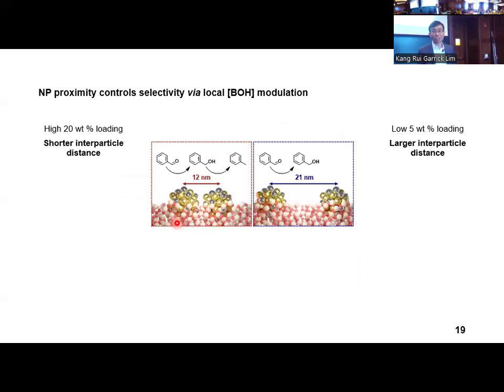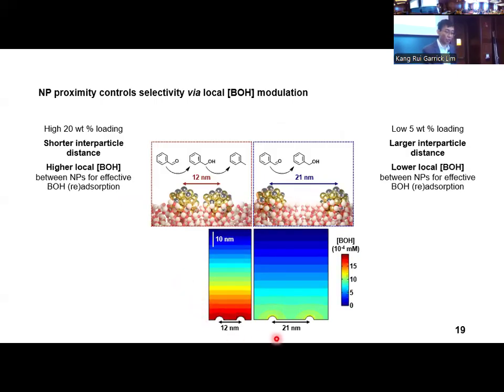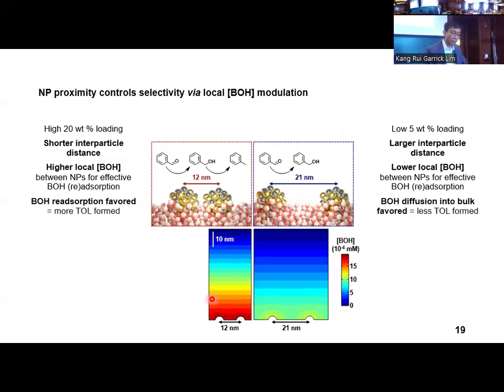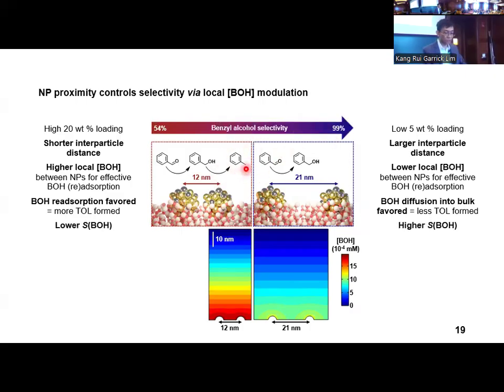Now we can combine our findings all together. Catalysts with a shorter interparticle distance exhibit an enhanced local benzyl alcohol concentration profile between the nanoparticles. Thus, a greater fraction of the as-produced benzyl alcohol is readily readsorbed to an adjacent nanoparticle or back to the same nanoparticle instead of diffusing into the bulk as free benzyl alcohol. This results in more undesired toluene produced and a poorer selectivity towards the desirable benzyl alcohol intermediate. Overall, this work illustrates that the same catalyst under the same reaction conditions can lead to different catalytic outcomes by simply manipulating the nanoparticle placements.